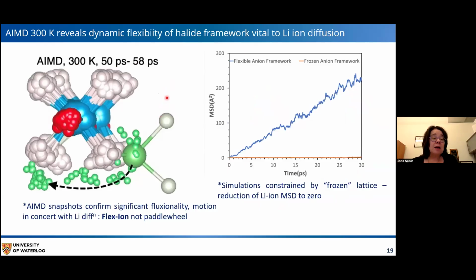And this is nicely caught by a picosecond snapshot where you can see the degree of wobble for the chlorine in this direction, and the oxygen, which is shown in red here. And this is then coincident with the lithium translation over these 8 picoseconds from one site to the other. So this is not a paddle wheel. This is really what, as I said, we call a flex-ion concept. And there's no evidence that this is a correlated motion, so to speak, but there's obviously some degree of connection between this fluxionality in the anion and the movement or the mobility of the lithium.